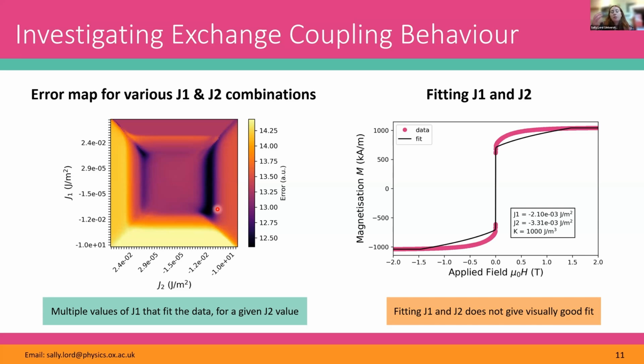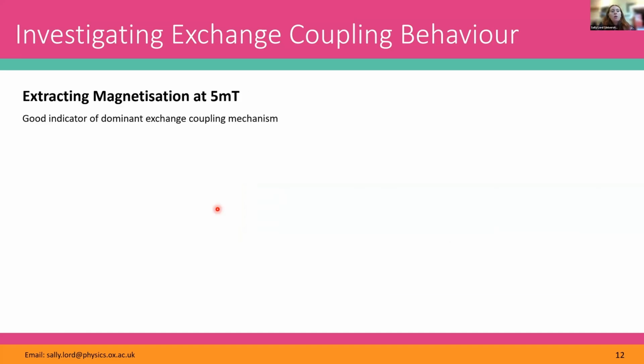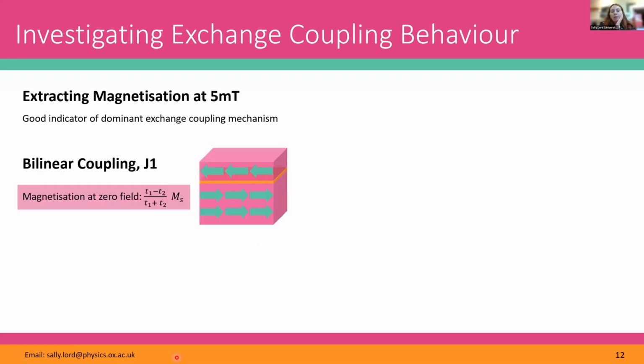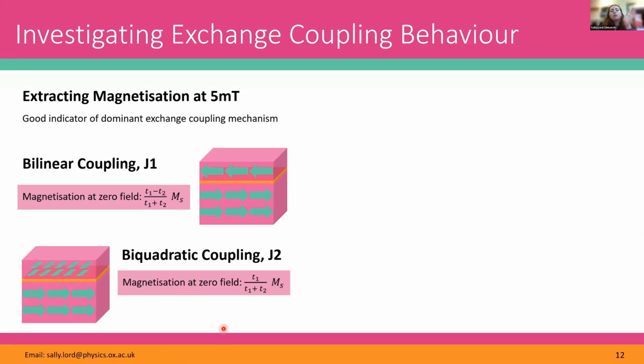So we went back to the experimental data to see if there was anything we could extract from the SQUID data to give us more of an insight into what the dominant coupling mechanism was in the system. So we went back to the SQUID measurements and we extracted the magnetization at 5 millitesla because we thought this would be a good indicator of the dominant exchange coupling mechanism. And the reason why it would be a good indicator is because the magnetization at low field would be different depending on whether you had predominantly bilinear coupling or predominantly biquadratic coupling.